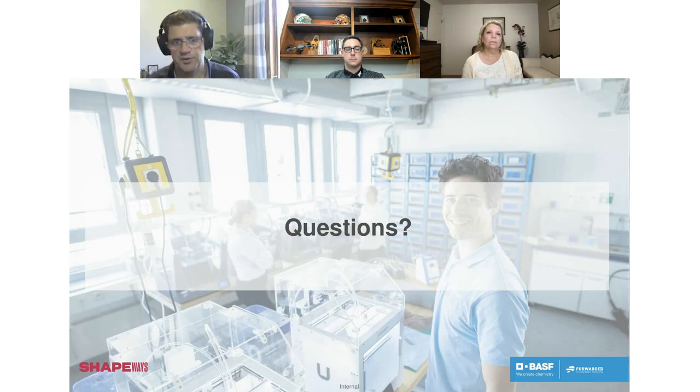We tested anywhere from 30 up to 100% regrind and found no degradation in material performance for those tests. So what that means is, let's say you're an OEM and you are printing hundreds of thousands of those little end effectors for work holding, for assembly tools. Every day your factory folks wear out one or two of those, they go into a bin, and you're collecting a fair number of these pieces. Well, rather than going to landfill, those can go to a production facility.